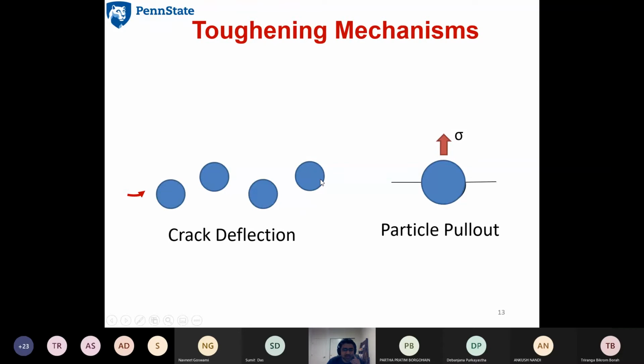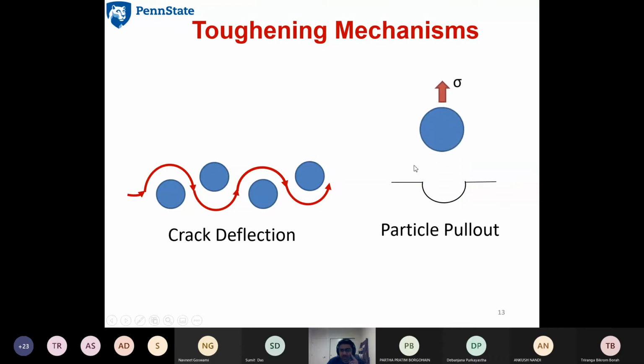There are two ways. To improve the toughness of the material, the crack should dissipate more energy. The first method that the nanosilica particles employ is called crack deflection. Instead of the crack traveling in a straight line, it deflects a lot. So instead of traveling a length of L, since it's wavy, the final length ends up being longer than L, so you're able to dissipate more energy. The other method is particle pullout. Here again, since the crack is not able to travel in a straight line, and energy is dissipated in pulling out this particle from the matrix, more energy is dissipated as the crack propagates.